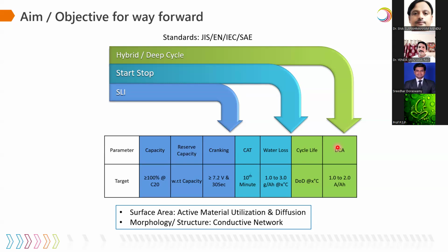Coming to hybrid and deep cycle. Deep cycle also covers the EV requirements. So deep cycle means it may be either 80% discharge or even 100% discharge. That's a deep cycle. And the dynamic charge acceptance, as I was saying earlier, with regenerative braking, where the battery needs to be charged even more aggressively. So as these evolutions are happening and the requirements are pushing batteries to perform under very stressful conditions, the surface area and the morphological structure of the electrodes are very critical elements.